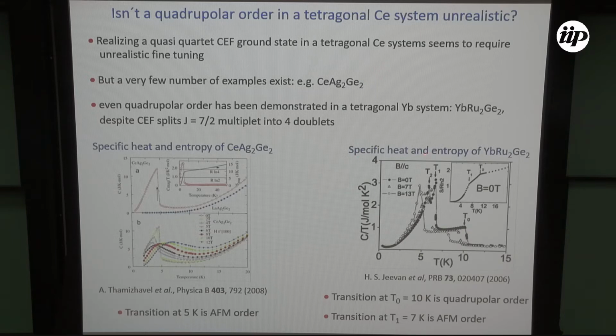But there is one case where we found even a quadrupolar transition, namely YbRu2Ge2. In ytterbium, one has the same problem as in cerium. Instead of 3 doublets, one has 4 doublets, but they should also be split in a tetragonal system, so there is no protection for a quartet. But in this case, we found from the specific heat an entropy of R ln 2 just at 10 Kelvin. And we proposed, based on the phase diagram and the susceptibility, that the first transition at 10 Kelvin is a quadrupolar one, followed by a succession of 3 magnetic transitions. It has been confirmed that indeed there is no magnetism here, but there is strong magnetism here. And last year it was shown that indeed this transition is a quadrupolar transition. So one can realize a quadrupolar transition in a tetragonal ytterbium and likely also in cerium systems.